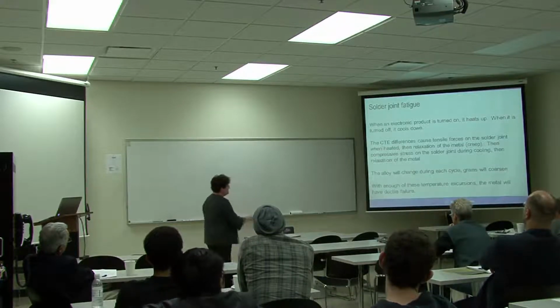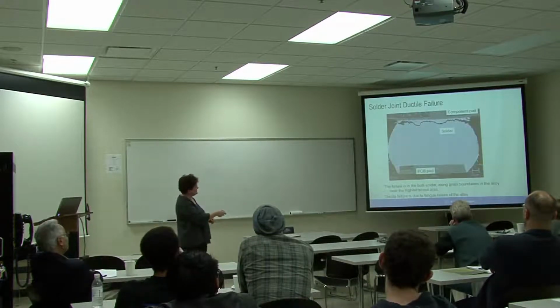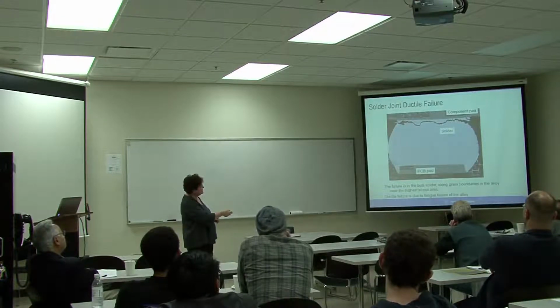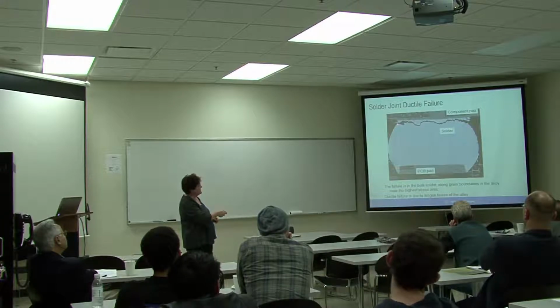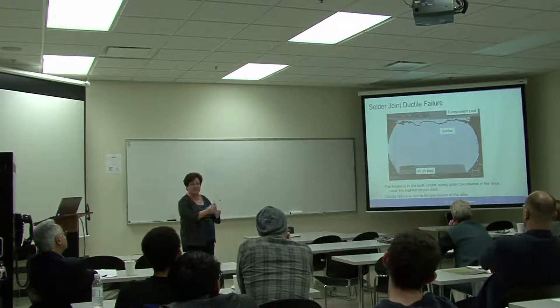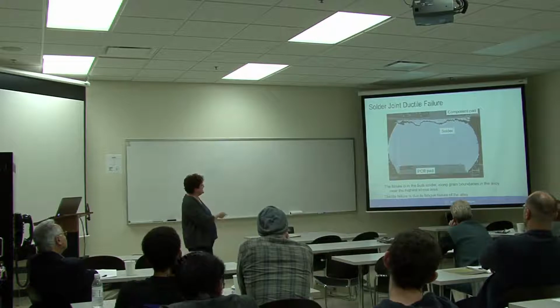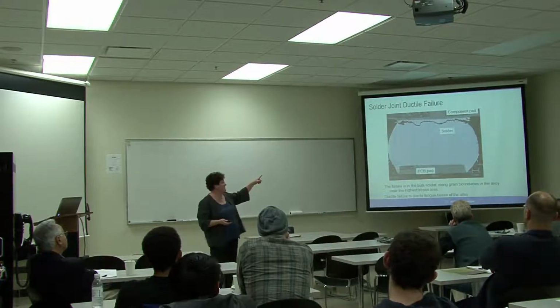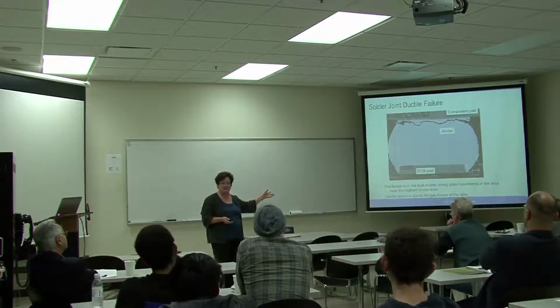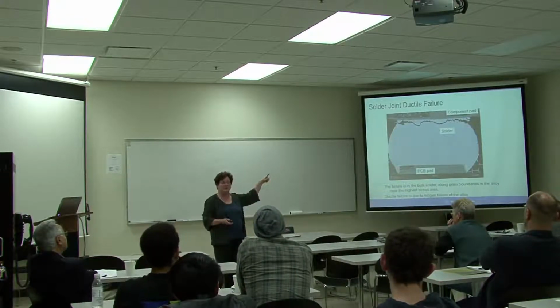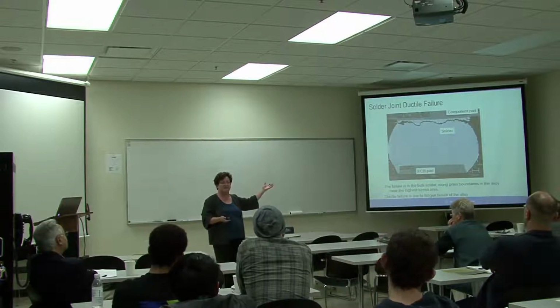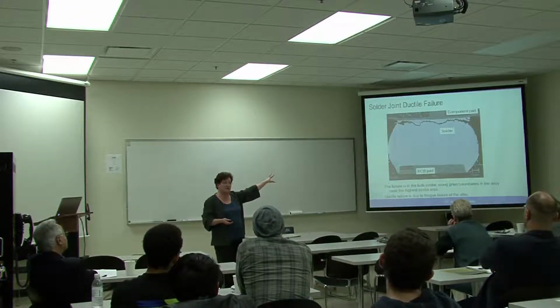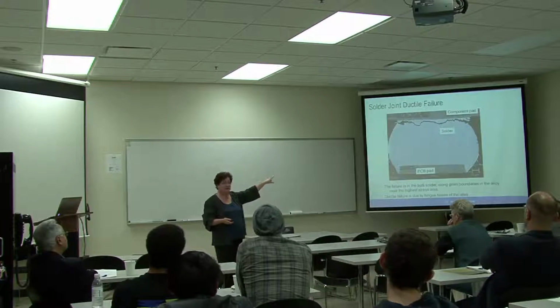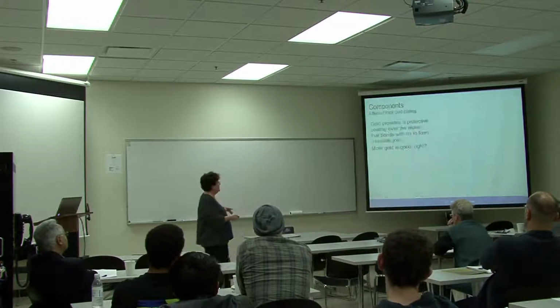So here's a picture of a ductile failure. It's following the edges of the grain boundary. It's at the point of highest strain, which is over here. Usually on the component side is where it has the highest strain. And yeah, it's just ripped along there. So we'll find those, not as much in real life because of the testing we do, but that's what we're looking for when we're doing a reliability test for long life. We're trying to figure out which parts fail faster in this kind of mode than in others.